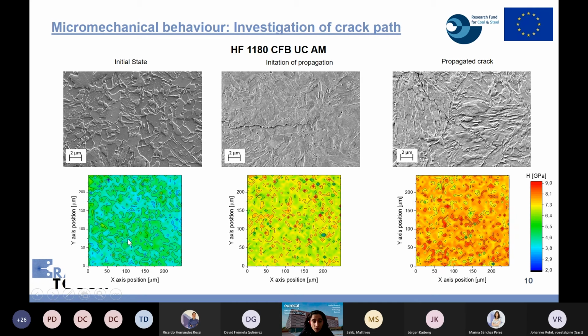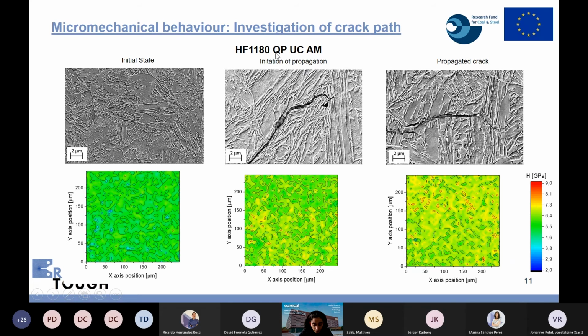Here we can observe in the mappings of hardness that hardness increases a lot if we compare with the other materials. And again, we can observe these little harder islands that are related with the TRIP effect of the steel. Finally, here we can observe the QP that consists basically of a tempered martensite. In that case, the pronounced needle-like morphology of retained austenite islands is a clear difference with the other steel grades studied in this project. Here, again, we can observe how hardness is evolving with the deformation during the propagation and initiation of the crack. And also, we can find little harder islands related with the TRIP effect.